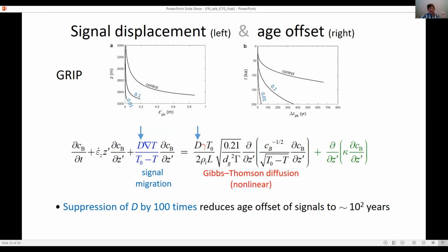Now, when we do prolong signal survival by blocking the veins, what we do is decrease D, but we also minimize signal migration. So when we allow signals to get to deeper ice and survive in amplitude, they don't migrate, as you can see from these blue labels. In fact, for the 1,000-fold label, there's a curve here that is basically vertical. So yeah, it's a catch-22 situation for the Rempel theory. When signals migrate because of an open vein system, their amplitudes decay before they can show the migration. If we slow the diffusion, we also slow the migration, so signals don't migrate anymore.